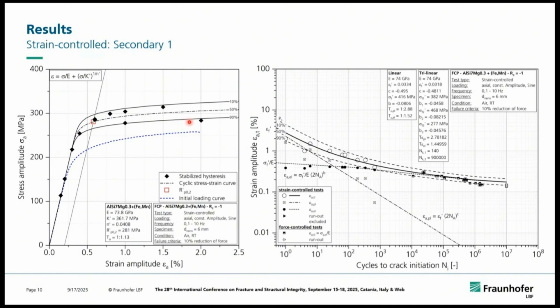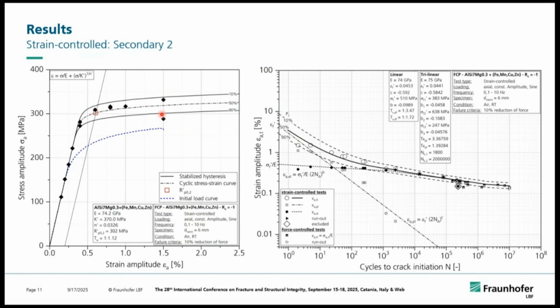Cyclic hardening is present here as well, but the effect is not so strong due to the fact that we have, in any case, for the secondary 1 and secondary 2 alloy, a bit higher tensile strength and a higher slope for those tensile test results. Secondary 2 was not really surprising, more or less the same results.